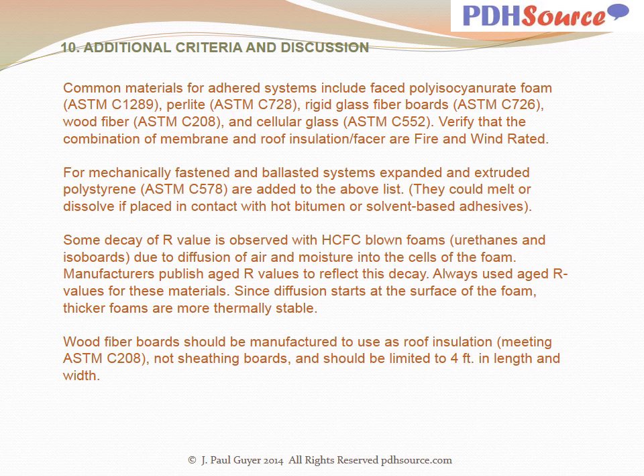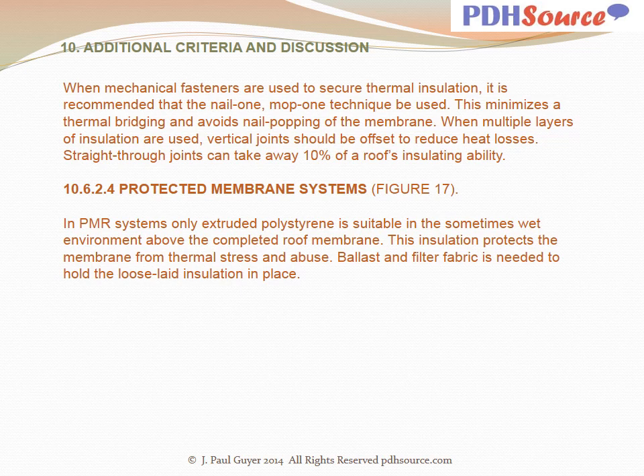Wood fiber boards should be manufactured for use as roof insulation, meeting ASTM C208, not sheathing boards, and should be limited to 4 foot in length and width. When mechanical fasteners are used to secure thermal insulation, it is recommended that the nail one, mop one technique be used. This minimizes thermal bridging and avoids nail popping of the membrane. When multiple layers of insulation are used, vertical joints should be offset to reduce heat losses. Straight through joints can take away 10% of a roof's insulating ability.